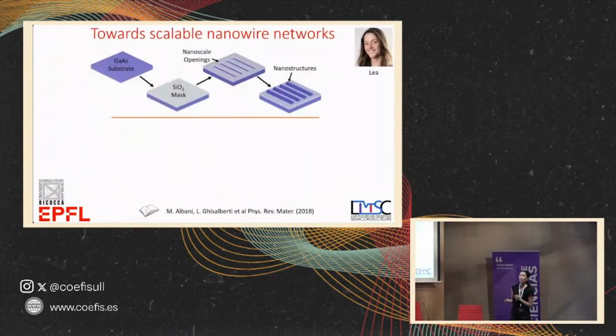So for this, we wanted to use this principle. We make the substrate in a way that we put the anti-sticking surface, the oxide, and we made slits to get the nanowires only grow there. It's not that easy. We want very high quality. So what we do is the following trick.